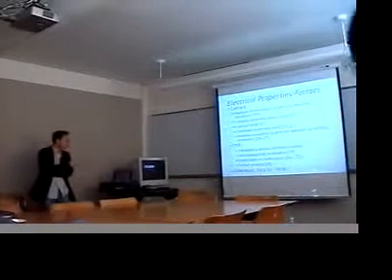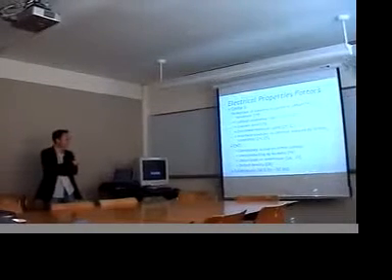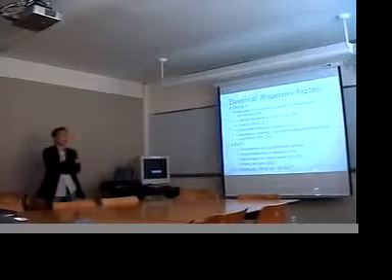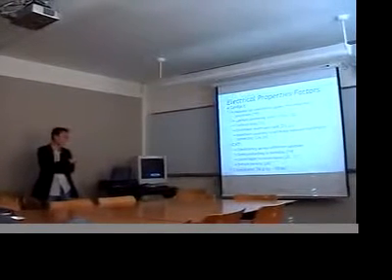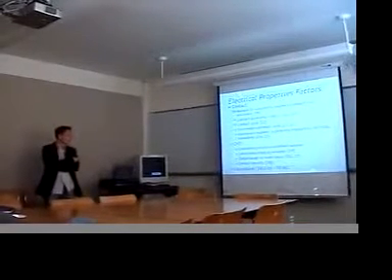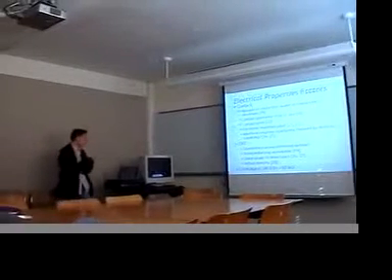This is not quantum. So I think 34 ohms is a bit too much. Only one paper has roughly this kind of value. If it's 34 ohms, you're looking at around 10 to the power of 11 ampere per cm squared, so very, very high current capacity. Most of the values that I find are usually in the tens of kilo ohms to 100 of kilo ohm level. The ones that we have in our process are typically around 100 of kilo ohms.